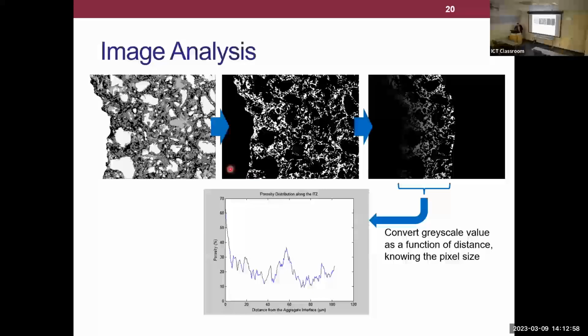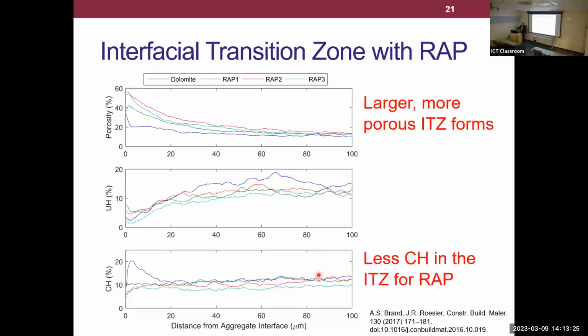What we have to do here is just use image analysis. I won't go through all the image analysis, but you basically threshold out what's the unhydrated cement, what's the calcium hydroxide, what's the porosity, convert it to a binary image, do some more image processing, and you can then get a gradient of these properties as a function of distance from the aggregate surface. When we do this over many images, we can come up with an average representation of what the ITZ looks like.